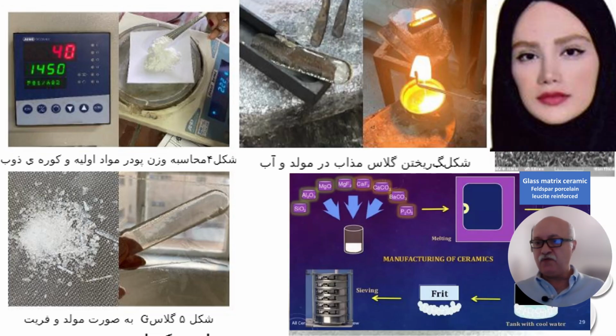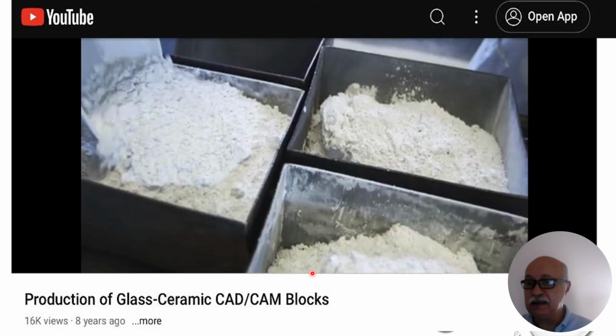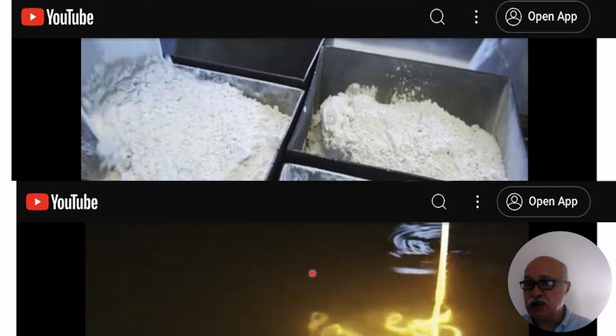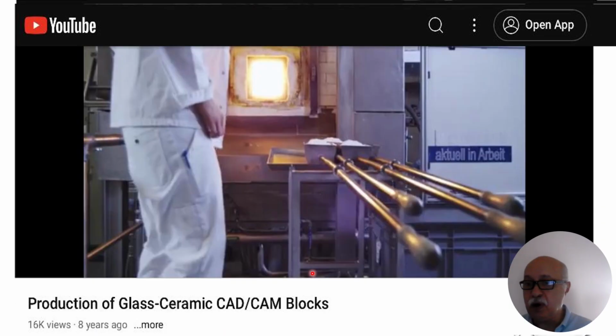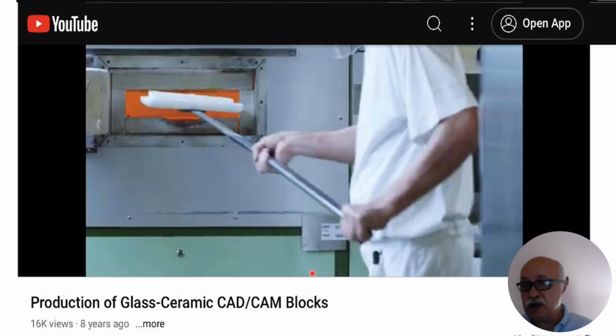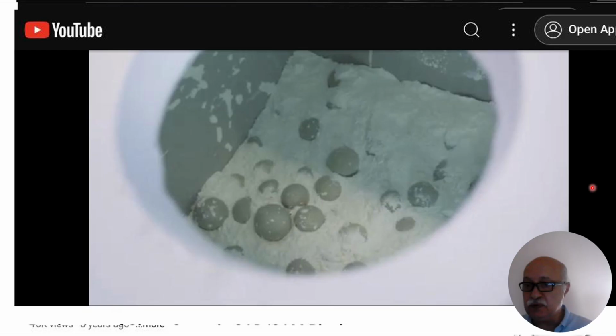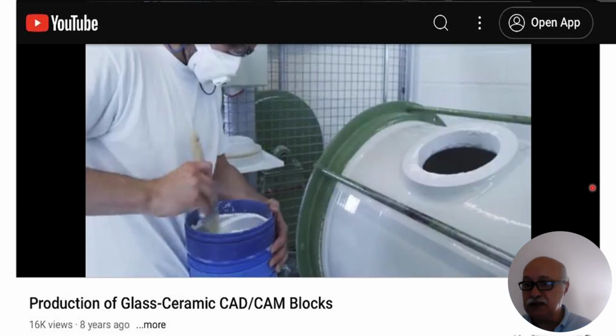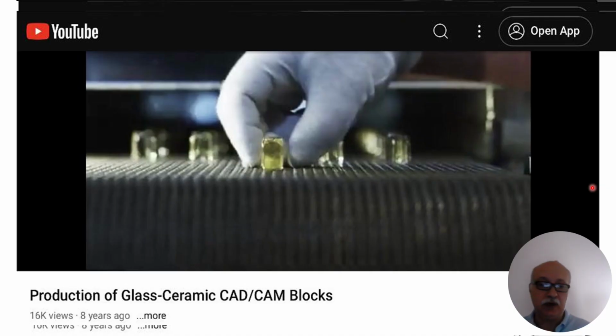Raw materials were weighed and put in a furnace. Temperature was increased to 1500 degrees. After 2 hours the melt is quenched in water or molded. Ivoclar Vivadent has a similar procedure of remelting and heat treatment to change the glass to glass ceramic, then ball milling and particle size reduction process is applied. Then hot isostatic pressure is used to manufacture the CAD-CAM partially sintered block.